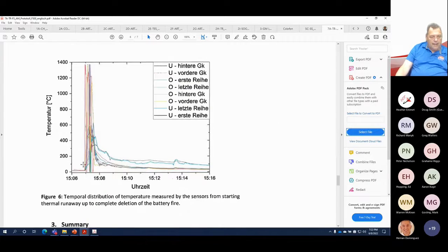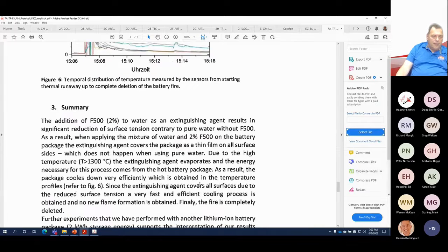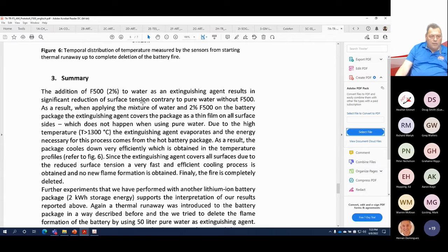This is showing the heat, the first 5 seconds, boom, the second 5 seconds. And again, after we stop the application of the F500, with plain water, we see that heat do this. It humpbacks and comes back up. With the F500, it keeps it down. They provide a summary here and say that it's due to surface tension reduction.